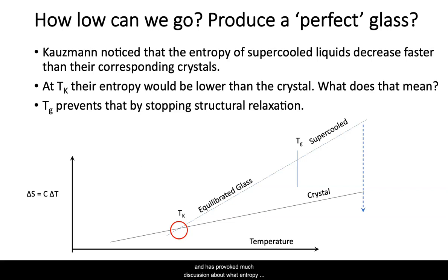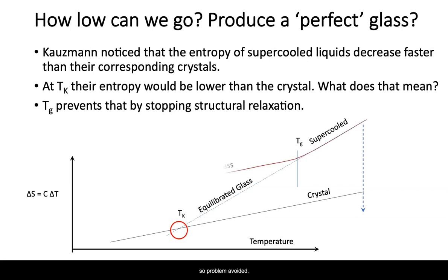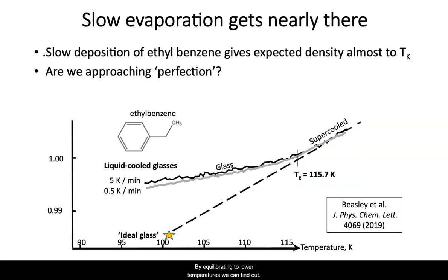It's provoked much discussion about what entropy means in a glass. At Tg, when the glass structure freezes, the difference in slope disappears, so the problem is avoided. But what if we could equilibrate at Tk? Is that an ideal glass? By equilibrating to a low temperature, we can find out. Slow cooling doesn't get you very far; vapor deposition gets further.